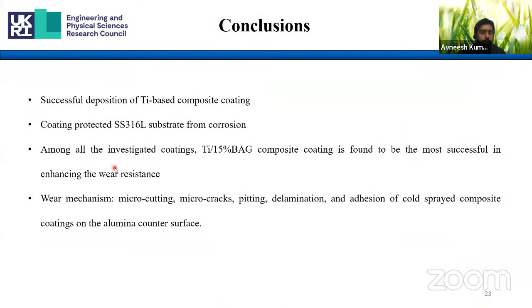So from this we concluded that we were successfully able to deposit titanium based composite coating on SS316L substrate, and a significant amount of baghdadite was retained in the coating. The coating protected the SS316L substrate from corrosion because of the formation of calcium oxide, silicon oxide, and titanium oxide protective layers. Among all the investigated coatings, the 15% baghdadite composite coating was found to be the most successful in enhancing wear resistance, because of its superior hardness. The wear mechanisms we found were micro cutting, micro cracks, pitting, and delamination, which are features of abrasion. We also found some mass transfer to the alumina counter surface, which is a feature of adhesion.